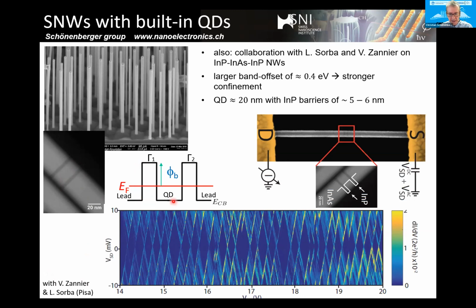And the indium phosphide has a larger gap than indium arsenide, and in the conduction band there's a band offset of around 0.4 electron volt, which means it's quite large as compared to low temperature energy scales. So you can make quantum dots with very strong confinement potential, quite locally well defined. And here below you see a measurement of Coulomb blockade diamonds using these quantum dots.